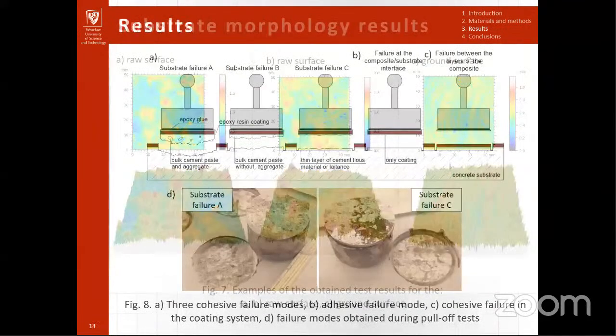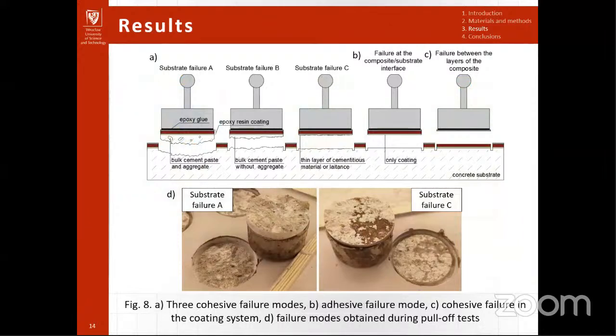We took the measurements of the pull-off strength at 3 points for each square on two types of surface. As shown in Figure 8, A, B, C, the standard distinguishes several possible modes of specimen failure. We have determined the type of failure for each measuring point. Examples are shown in Figure 8D. For the raw surface, failure in the thin layer of cementitious materials was observed at 4 points. In the remaining points, the failure occurred at a greater depth in the concrete.